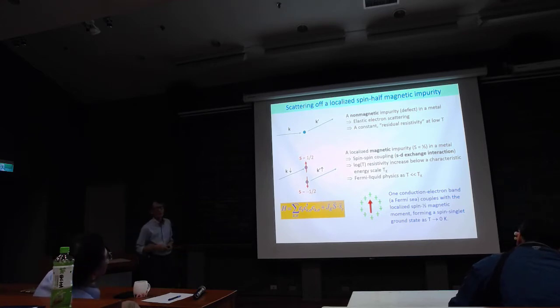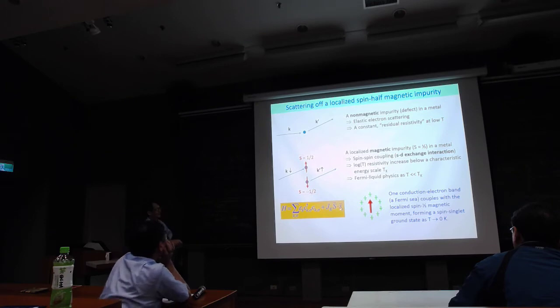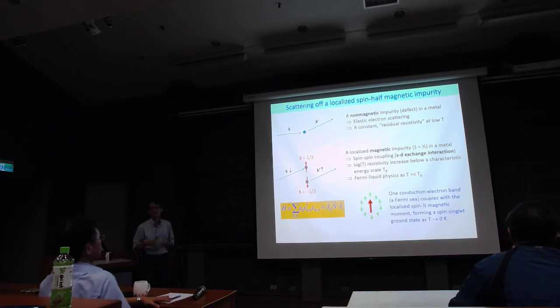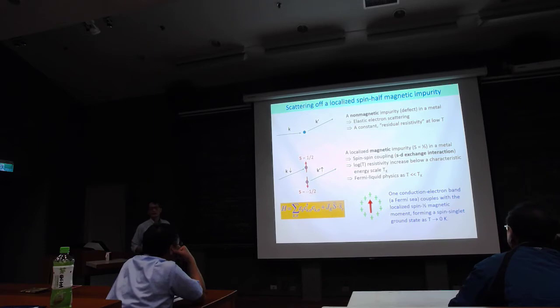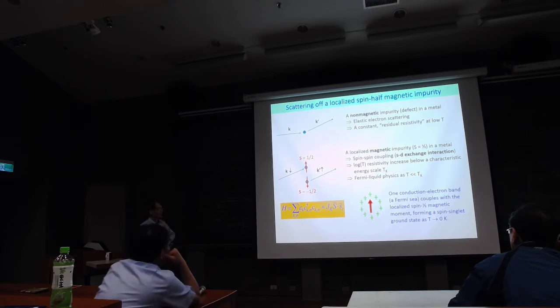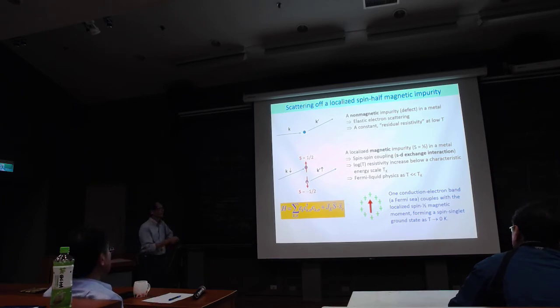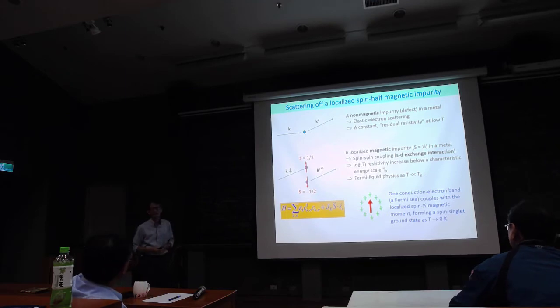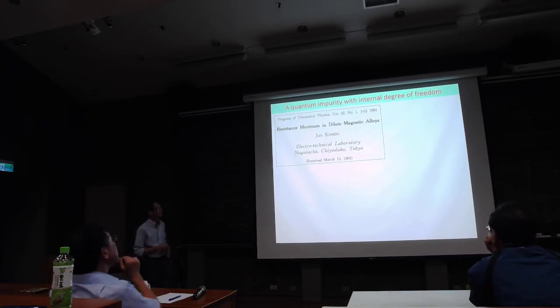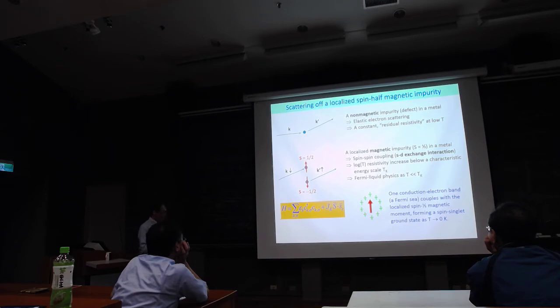And if you go through all the calculations, you will have this extra term, the s-d exchange: conduction electron spin, local moment, this impurity. And if we calculate this exchange interaction, that will give you this resistivity increase at very low temperature. So that is the original idea of the Kondo effect. And when it goes to zero temperature, the local moment will be screened by conduction electrons. So they form a spin singlet ground state, and this returns to a Fermi liquid ground state. So this is the theory by Kondo in the 1960s,